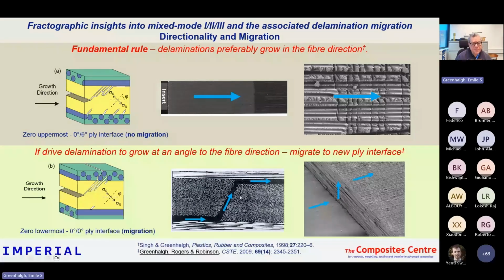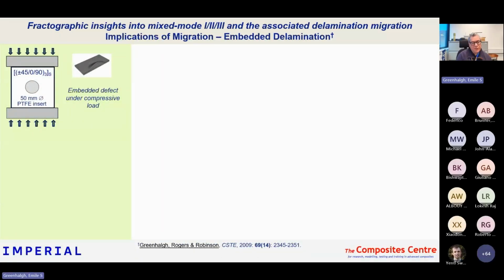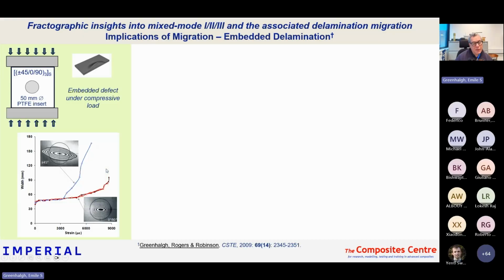This means that trying to measure the fracture toughness of a multi-directional interface can present problems. Because if you have this situation where the upper ply is in the growth direction, then you can characterize the toughness. But if it's not in the growth direction, you get migration and you no longer get a pure delamination surface. How this manifests is illustrated here. This is some work that we did on an embedded delamination in a composite laminate under compression. It's a quasi-isotropic laminate with a 50mm diameter defect. This is showing the damage width against applied strain. The particular one that I want to focus on is the one at the 0/90 ply interface.